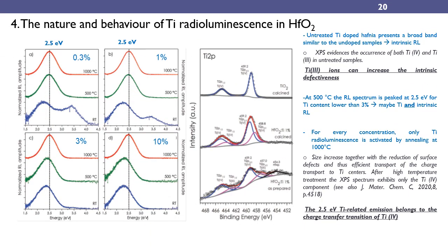The picture resulting from the radioluminescence spectra of hafnium oxide doped with titanium is complex, but for one more time it explains clearly the strong importance of good doping strategy and good annealing routes for the control of the light output of nanomaterials. If we consider the untreated hafnia, we can notice that the luminescence features are similar to the ones of undoped hafnia. This means that when the sample is not treated, the intrinsic defects play the major role in driving the luminescence behavior.